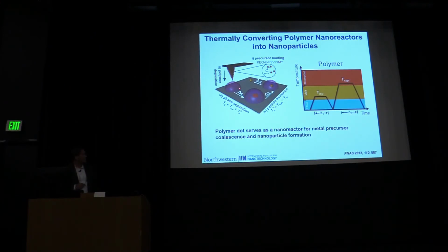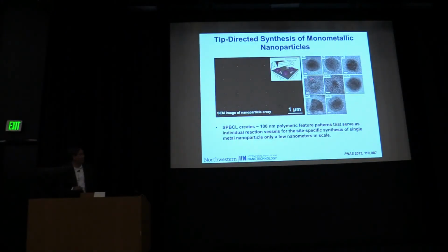And it turns out there are many things that are going on, but a couple of key things that can enable synthetic design. One is that in the early stages of heating these reactors, you drive out water, and that ultimately causes precipitation of the salt. We were, of course, just ramping right to the gold particles in the first experiments that I showed. But what we found is that if we slowed this process down, we could cause the salt to precipitate, get everything closer together. Now, lower the activation barrier for coalescence, raise the temperature, blow away the polymer, reduce the metal ion, and ultimately lead to individual particles. When you do that protocol, you now can begin to make almost anything. Gold, silver, platinum, palladium, iron oxide, cobalt oxide, nickel oxide, copper oxide as examples. And again, in mass.